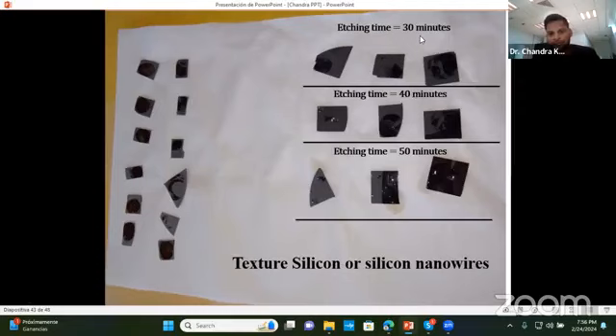We deposited earlier for 0.5, 1, 2, 5, 10 seconds for texturization. But when we are planning to fabricate porous silicon or silicon nanowire, we have to use a high etching time, like 30, 40, and 50 minutes, to texturize the silicon. That comes in the category of either porous silicon or silicon nanowire.